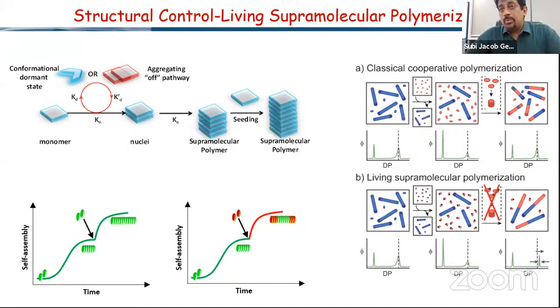What was the problem in supramolecular chemistry or supramolecular polymers in achieving this structural control? If you look into supramolecular polymers, you see that monomers come and keep growing, right? So there is no termination in principle. You can add more monomers; ideally, it should grow endlessly. But one of the problems, which is again an outcome of the mechanistic insights in this field, is that we talk about chain growth or cooperative mechanisms. So we know that it has two steps: nucleation, and then obviously propagation, a nucleation-growth mechanism.